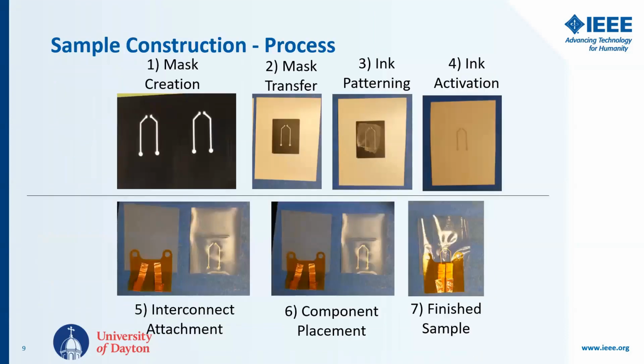So our construction process is to first manufacture the samples. We use a vinyl cutter to cut a mask out of adhesive-backed vinyl in the shape of the traces that we want to pattern onto our TPU sample. This mask is then transferred to a piece of TPU, and conductive material is applied to the mask with the razor blade or blade coating method. It's used to flood the entire void in the mask and level the surface. The mask is then removed, and the conductive material is strained to activate it, rupturing those nanoparticles of liquid metal, allowing the liquid metal to spill out and percolate through our network.